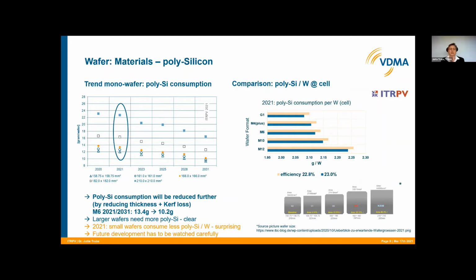But we asked for the different wafer sizes. So how much silicon do I really have to use to get the bigger wafers? Of course, larger wafers need more polysilicon. This is clear. But if we count per watt on the wafer, we see that the bigger wafers need more silicon. This is a little bit surprising, but we will observe and watch this in the future. That's maybe one reason, because the technologies are not as mature as for the smaller wafer sizes.